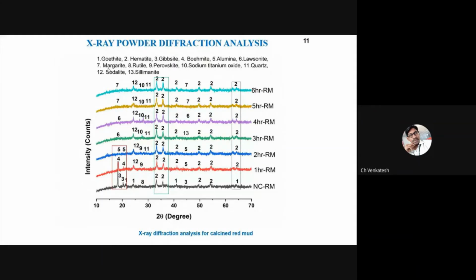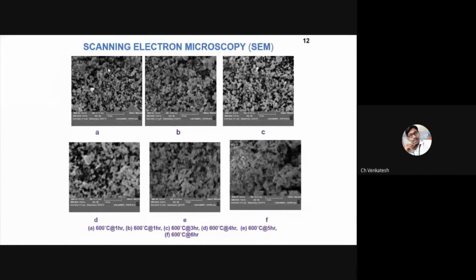the iron oxide. Similarly, here we have also conducted scanning electron microscopy analysis to know how the surface morphology of the red mud particles varies with respect to the temperature. From this study, we have identified that at 2 hours of calcination, the particles are poorly crystalline. Here you can observe in diagram A the particle size compared to A and B. B is much smaller than A, and after B the particle size increases.